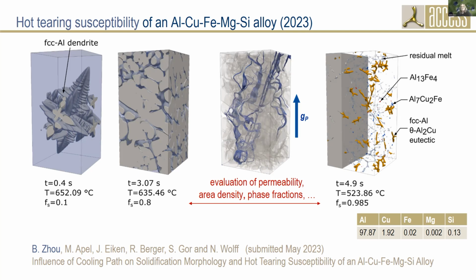Just as I understand correctly, when you're simulating the solidification, you said you had a fluid flow simulation between the dendrites, basically. Yes, the liquid is also moving. But it's not at the same time during the solidification. At certain moments during the solidification, we took the structure and then we imposed pressure gradients, and Beiju did it, and then evaluated the Darcy flow from this in different directions.